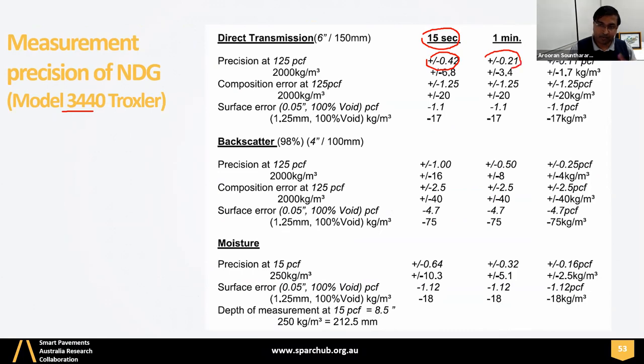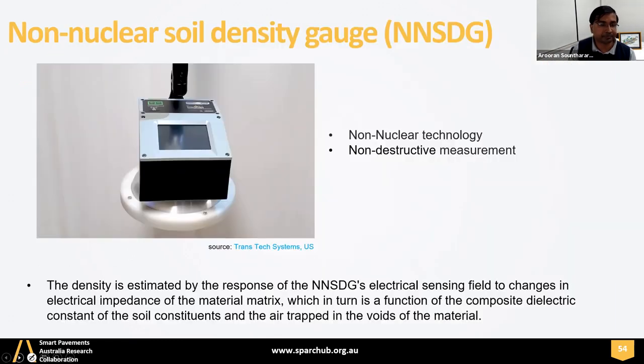So in a nutshell, I don't want to go through all these points here. What I wanted to emphasize here is, as the time increases for the gamma source to provide more radiation, the accuracy of the density measurement also increases, as you saw here, right? 4 minute, 1 minute, 15 seconds. However, due to the time limitations in the field, you've got to do a lot of density testing from one lot to another lot, and minimum 6 tests per lot as a construction quality control. Typically, people select 1 minute as the typical radiation time. But in research, we normally go for four minutes, as we don't have any time limitation or construction limitation.